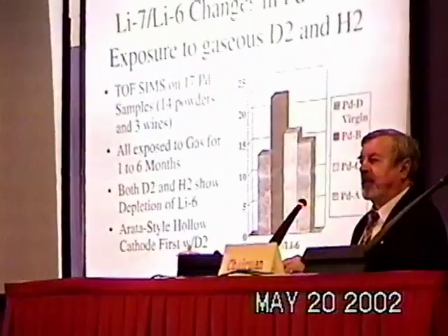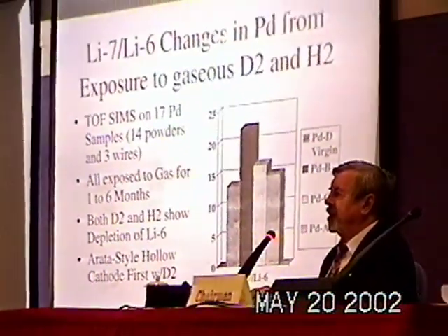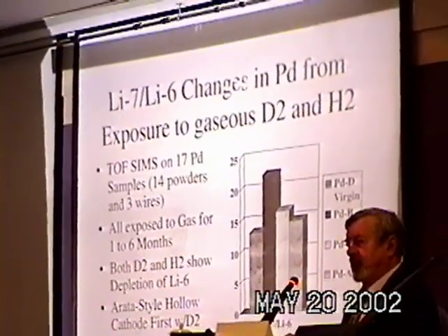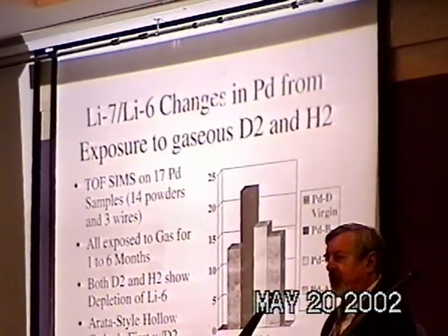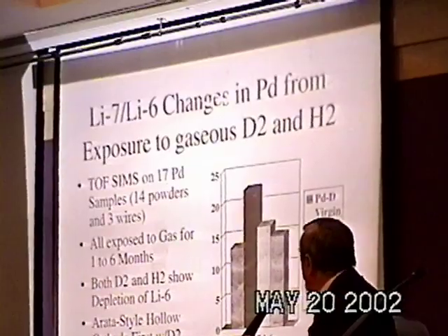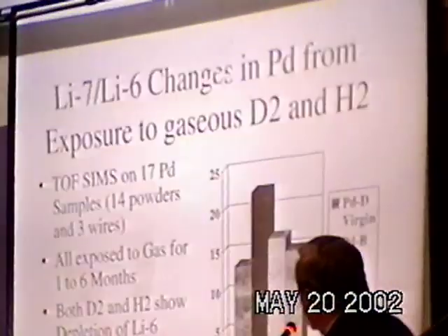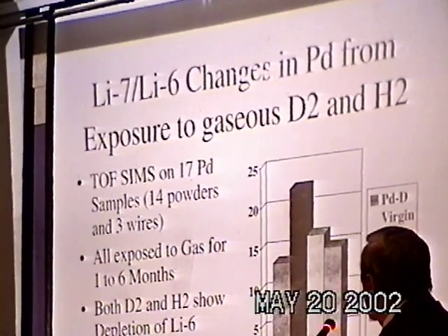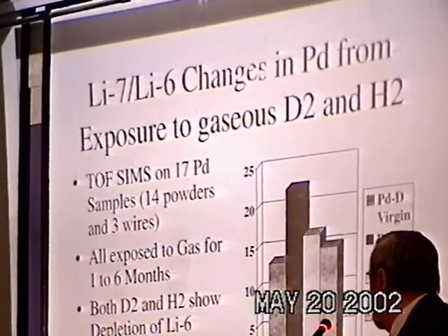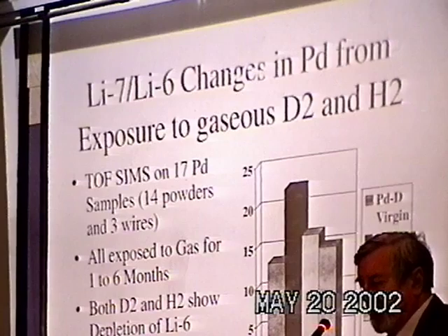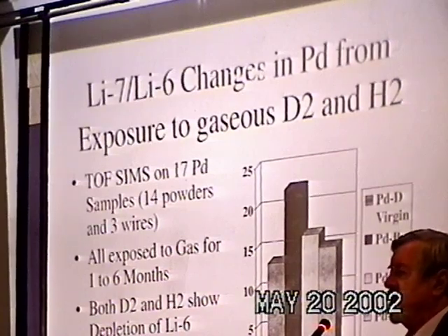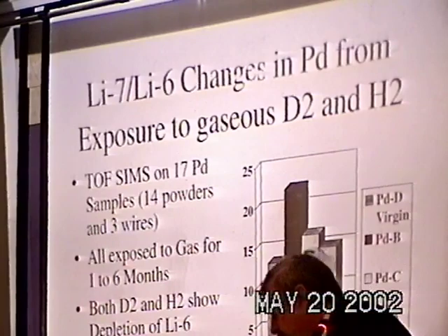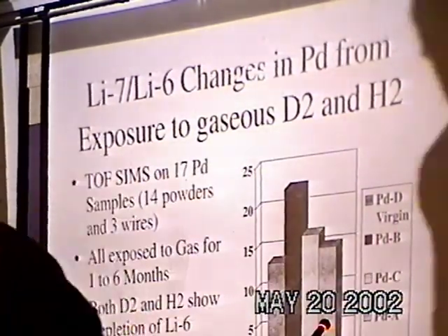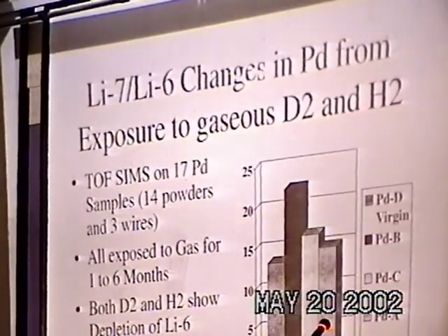I said, well, maybe it's the impurities in the palladium that make this thing possible. The first thing we came up with is boron 10, which was obviously already there at about 100 parts per million. And I pursued that for a while. And then more recently, I observed zinc and gold and iridium and silver and cobalt in these samples, similar to Dr. Arata's, in fact, some of his samples, which were only exposed to gases.